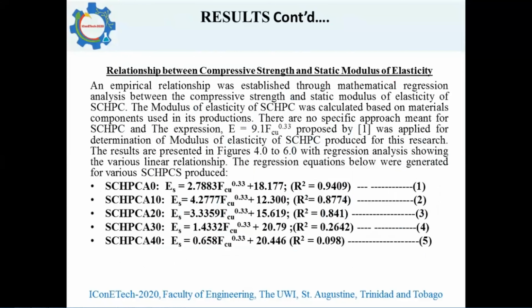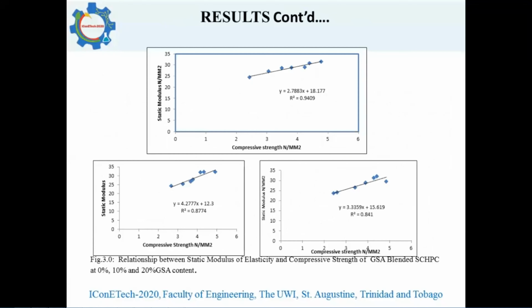The empirical relationship was established through mathematical regression analysis. The modulus of elasticity was calculated based on the material components used in the production. There is no specific approach meant for this. The expression in the BS 8110 code as proposed was applied for determination of modulus of elasticity, and it gives us a regression model of up to 20% of 0.841, but from 30 and 40%, you're having a different regression. The graph shows the relationship between static modulus and compressive strength of GSA blended at 0, 10, 20, and 30.